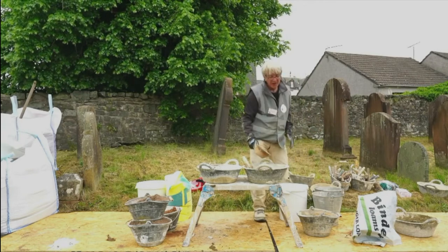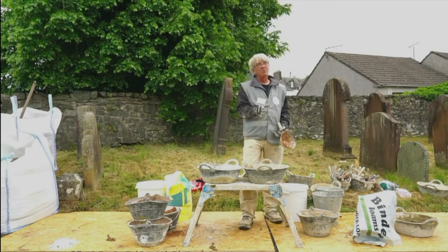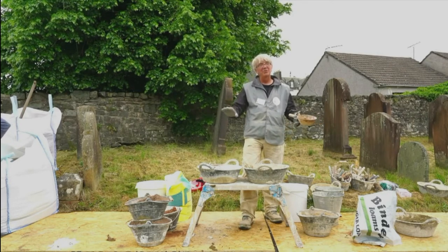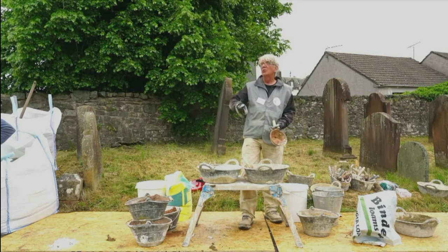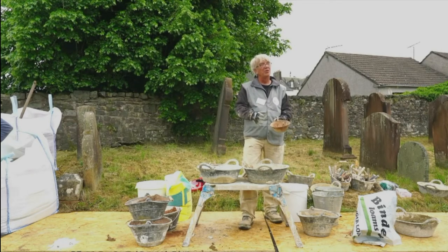And this is the point. Whether you're making lime wash, lime putty, or this, you slake with given volumes of water. Once the slake is complete, and that's the critical thing, which it substantially is, then you can add whatever water you need according to the purpose you're putting it to. But only after it's slaked. Don't put in all that water that you know you need.